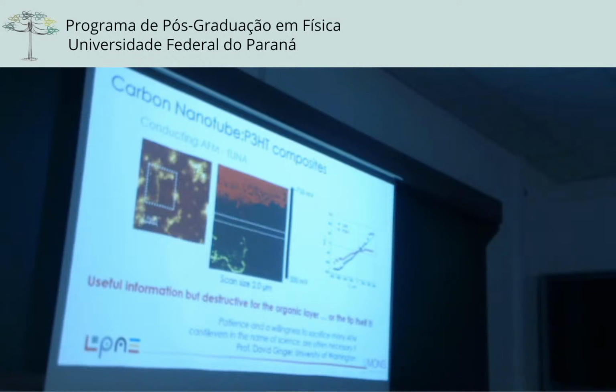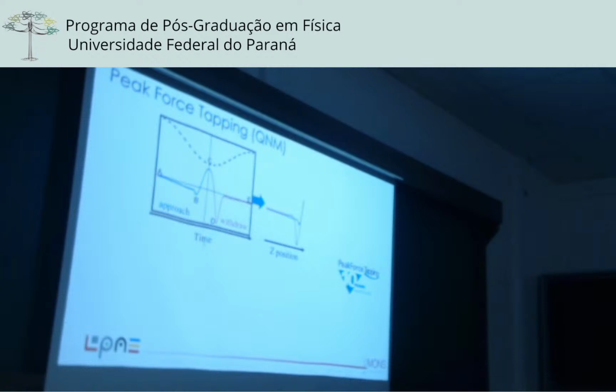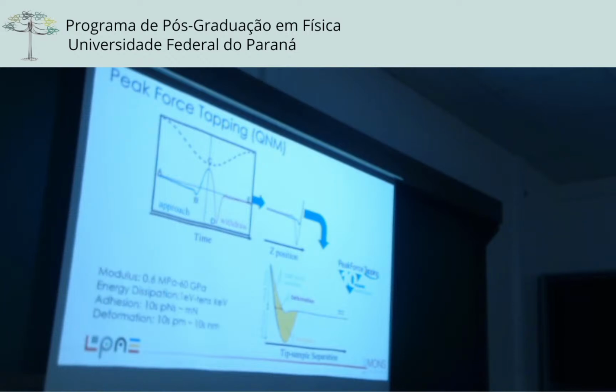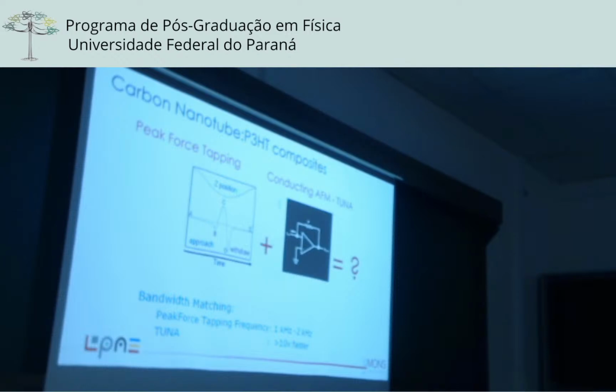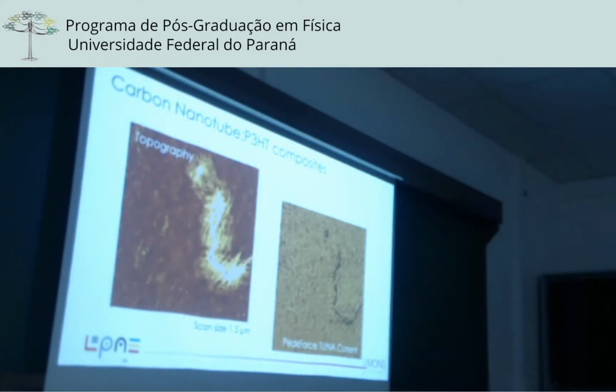So the idea is to try to mix different things, for instance, using PeakForce, which is a way to make some spectroscopy. So we have a spectroscopy, and when the tip is in contact, you are measuring the current. So you combine mechanical and electrical properties, and this is PeakForce Tapping and PeakForce TUNA. Okay, so in this case, we can measure the current. Once again, P3HT, carbon nanotube. We check that we indeed have these fibers of 16 nanometers. This is the topography, this is the current, and now we can start to make physics.